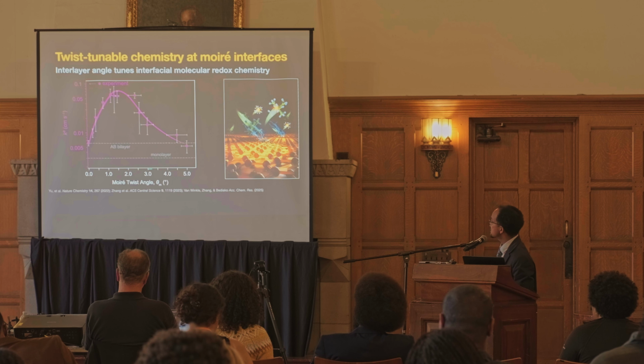And to cut to the chase, what we see is that we can control the rate at which the chemistry is taking place by controlling the angle between these graphene layers. Simply, you take the same material and you just twist it, and at different angles, it behaves chemically, in terms of interfacial chemistry, completely differently, at one angle versus another.